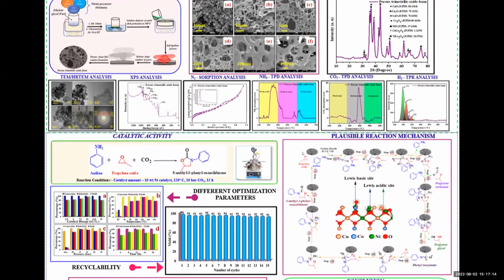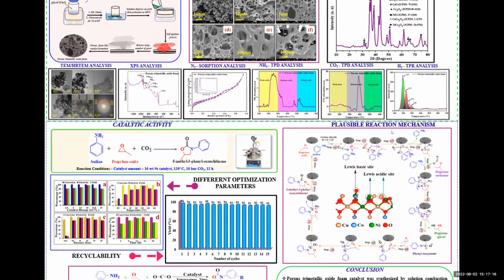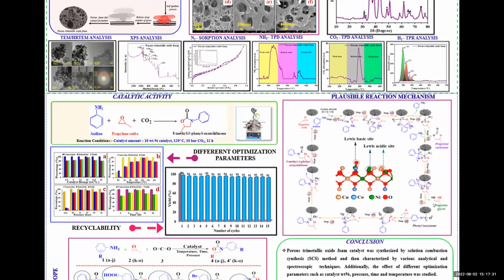Based on the characterization and experimental results, we predict the possible reaction mechanism for oxidation synthesis. Here, the initial reagents react with the catalyst surface. The first intermediate, cyclic propylene carbonate, is formed. After that, the propylene carbonate reacts with the aniline molecule. By elimination of propylene glycol, the secondary intermediate, phenyl isocyanate, is obtained. In the reaction mixture, again the propylene oxide interacts with the phenyl isocyanate. Finally, by the ring closure process, the final desired product is obtained. And finally, the catalyst surface is available for the next recycle.